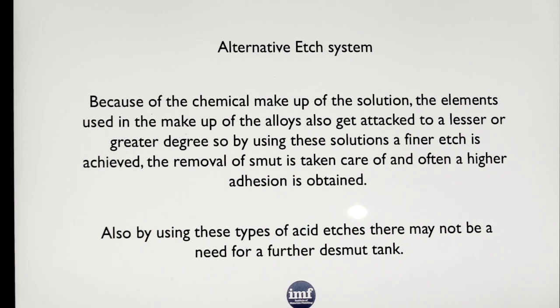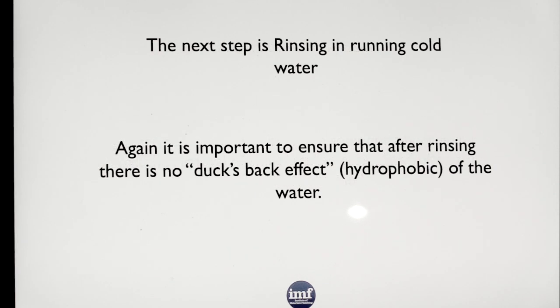You don't get any smut. It dissolves the smut straight away, and you're left with a very clean etch. If you pass that one around, that actually has been etched for 4 minutes in one of these fluoride etches, and that surface is then good enough to electroplate on to get you a good bond. Okay? Again, after you've etched it, you must rinse it, make sure that there's no water breaks on the surface, and then you move on to the next step.